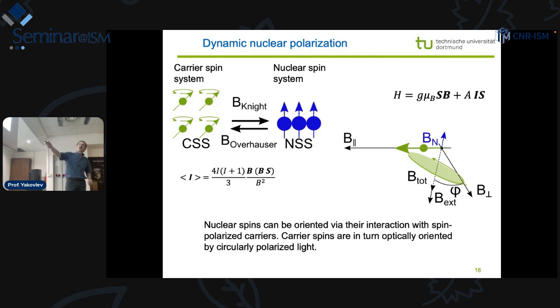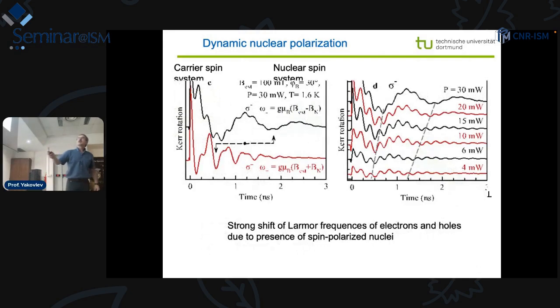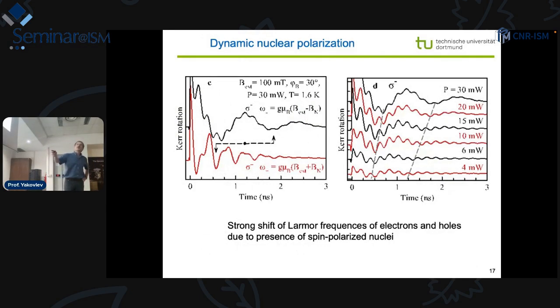So we can generate a photo-induced additional component of the magnetic field in the crystals, which adds up to the external magnetic field. And one can measure this component. It's measured here. What is shown here is pump-probe dynamics. So we should take care about the precession period here. And in one case, we use a tilted angle. We need the tilted angle in the case that the nuclear polarization is induced not perpendicular to the external magnetic field, but at some angle to the magnetic field.